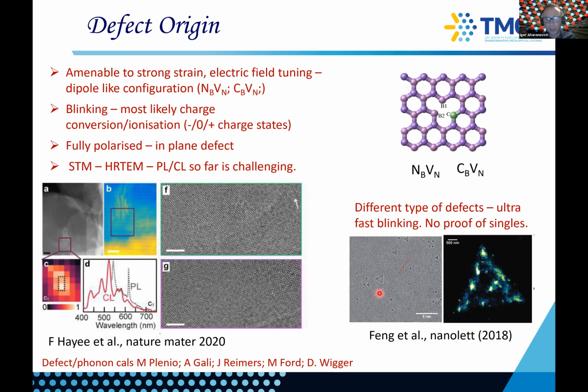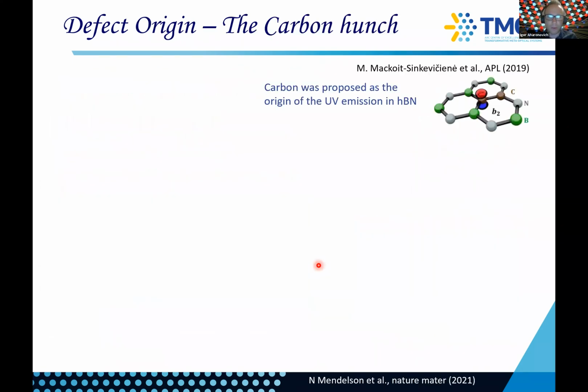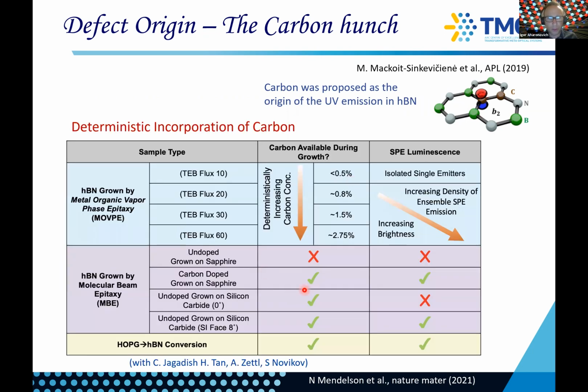But these techniques are now particularly appealing because for many years, people couldn't make a sample thin enough to really correlate between an STM or SEM image, STM or TEM image, and an optical image. So we decided to tackle it from a different side and really try to grow deterministically and pretty much eliminate everything else. And we started with carbon. And so carbon was proposed as a source of UV emission in hBN. And so what we did is, and don't worry about the details of the table, we decided to grow hBN using metal organic vapor phase epitaxy, MOVPE. And we chose this method because you could easily increase the carbon concentration. So you can go here from a very dilute sample to a very high sample, and TEB is just a carbon precursor.